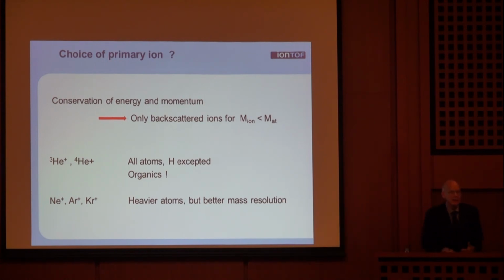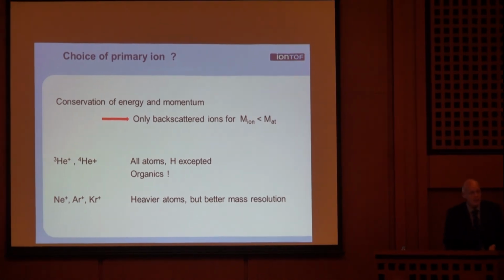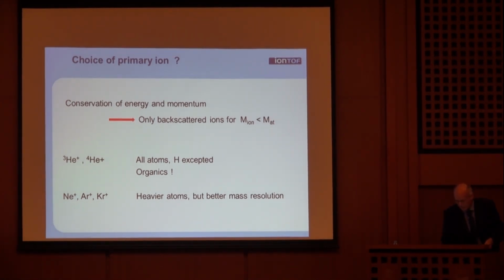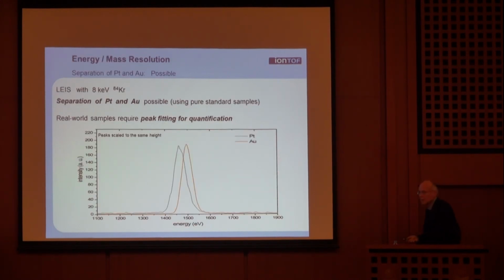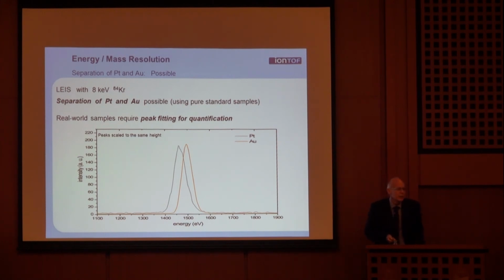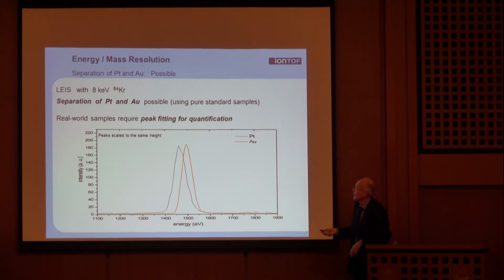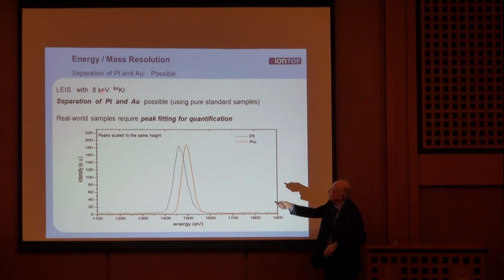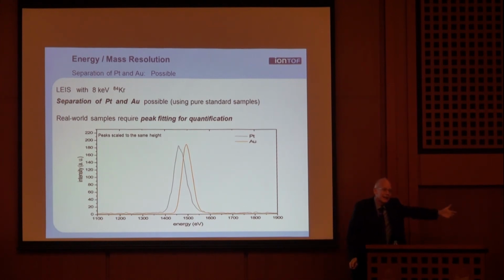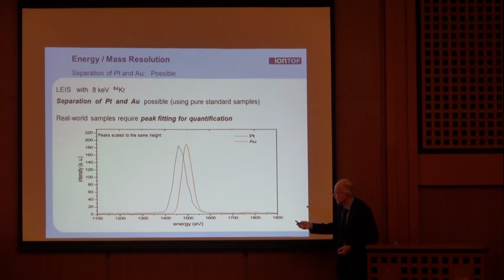Your mass resolution gets better, sensitivity gets better, and so for catalysts we very often use these ones like neon and argon. This is an example where we do, together with various companies also in catalysis, we look at catalysts that have heavy elements, and sometimes they have platinum and gold. And the problem is that the peaks of platinum and gold overlap. They are heavy and they are not easy to separate. But here we use krypton 84, so a very heavy ion, and then you can see that even on a real catalyst, if it's clusters of platinum or gold, we can see the difference and then deconvolute it.